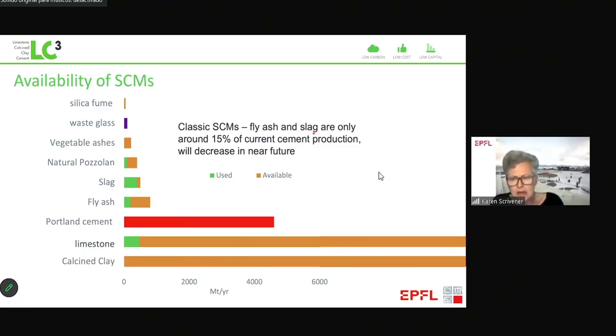So slag in particular is a very effective SCM. You can replace 70% or more of cement by slag, but worldwide we only have 8% of slag compared to cement. So now, if you want to use more slag in one place, you're just taking it away from another place, because 95% of that slag is already used. So where else can we go?